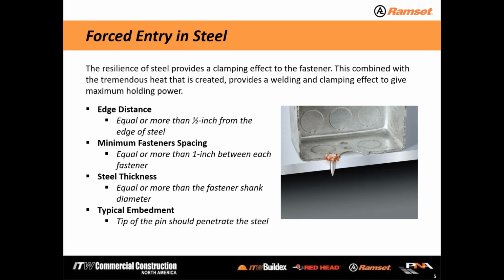If you've been out on a particular project or looked at some of the steel beam thicknesses, they go up an inch or more in thickness sometimes. So we can't always shoot through that. Generally, you can shoot through 3/16, quarter, 3/8. Once you get to about 1/2 inch thick worth of steel, you've got kind of a partial penetration value, and you're not really going to get too much. You're not going to get into through steel much thicker than that. And it really has to do with the power of the tools that are available in the marketplace today. So next slide, please.